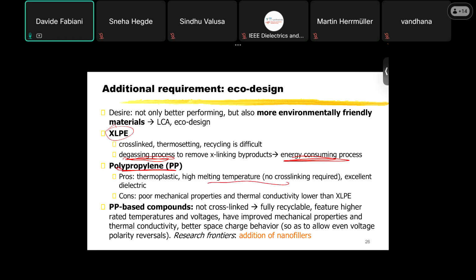The only problem is that the mechanical properties are quite poor. It's a very rigid material, and also the thermal conductivity is much lower than the XLPE. But now there are some polypropylene compounds using also elastomeric material or other material, not cross-linked, that are fully recyclable. They have a higher rating temperature, they can be used at higher voltages, and also they can have good mechanical properties and thermal conductivity. So the research frontier for this kind of material is also the addition of nanofillers to improve further the properties of these polypropylene-based compounds.